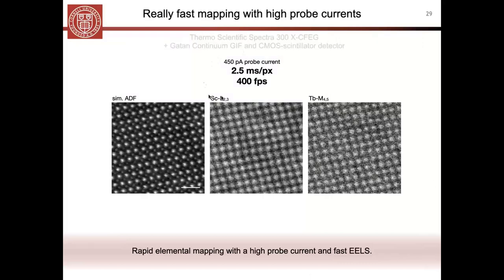We can start by looking at the same conditions that I showed you for the previous cryogenic EELS map. So 2.5 milliseconds per pixel, which is about 400 frames per second of the detector. But frames here is now referring just to a single spectrum, not to one EELS frame. Running at 2.5 milliseconds per pixel, but now, going from the results I showed you before, increasing our probe current by a factor of about 4 up to 450 picoamps, you can see that in this case we have very high signal to noise, very nice atomic resolution EELS maps of the scandium and the terbium.